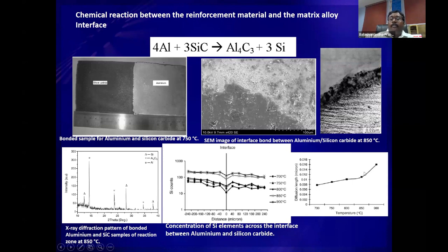We have also computed the diffusion length, that is, how far this Al4C3 will penetrate, and it would form up to a 0.016 micron layer thickness. That means it's a very fine precipitate, but the effect would be a very adverse one. Here it says that with increasing working temperature, the melt temperature, the length of the diffusion is also high. That means you can form some good thickness layers of precipitate which cover the particle. As a result, the permanent bonding is stopped.